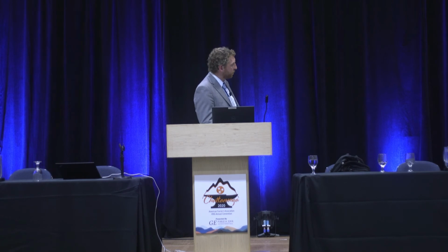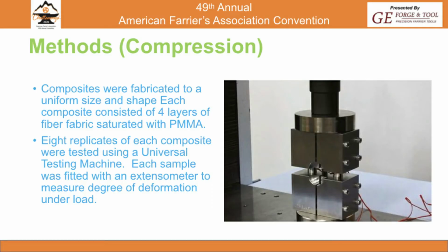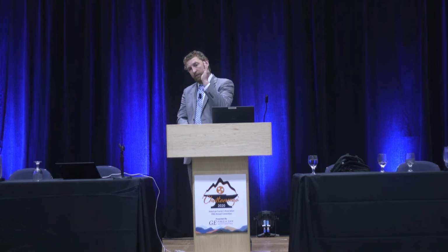And then from there, the last portion we studied was compression. So again, it's a jig, so 8 replicates of each one of the repair materials. Again, 4 layers, all made in the exact same way. We're putting a jig, and essentially what the jig does is it holds both ends of the pieces as close as you possibly can, and then the machine pushes this way. And so you'll see something does specifically happen to these things. So they do delaminate. So you're taking them, you've got layers of polymethyl methacrylate, the fabric, polymethyl methacrylate, fabric, polymethyl methacrylate, fabric around them. So what happens is when you start compressing them, they blow out this way. So they kind of delaminate.